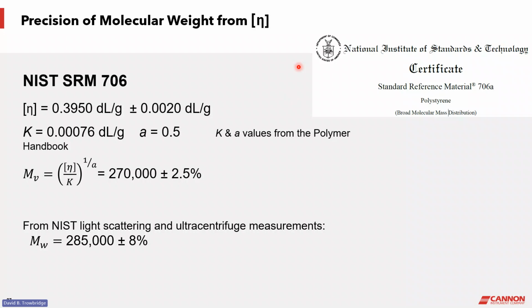Now, I should also use this slide because it describes the precision that's available, not only the accuracy, but the precision of the DSV measurement. This is data that was obtained from the National Institute of Standards and Technology on a special reference material they have. It was a polystyrene 706 they referred to it as, and they measured the intrinsic viscosity, and I took K and a values out of the Polymer Handbook for polystyrene and calculated a molecular weight using the Mark-Houwink equation and these K and a values from the Polymer Handbook, and I got a value for molecular weight and an uncertainty.